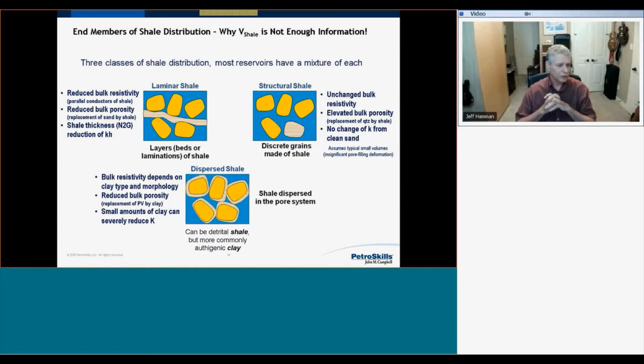It will also reduce the bulk porosity because we're replacing, say, a 30% porosity sand by some layer of, say, 10% porosity shale. So overall, the bulk porosity is going to vary as a function of how many shale layers there are, or what the volume of those shale layers is in the interval.